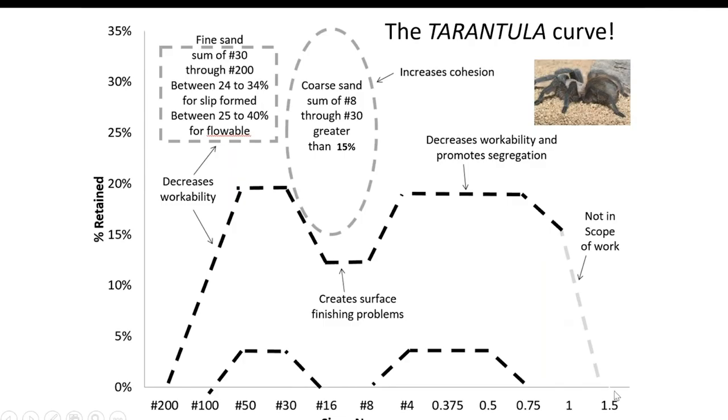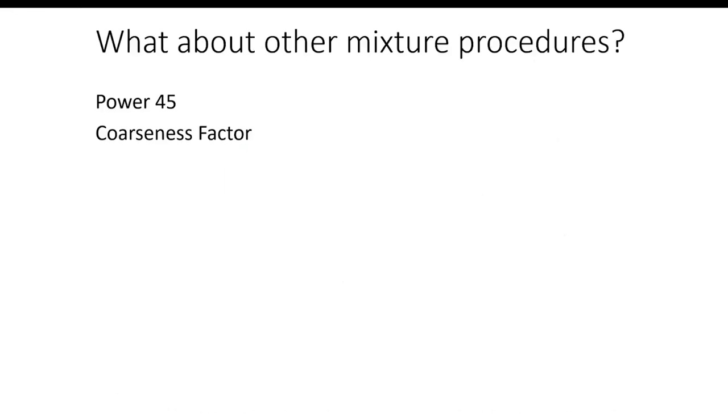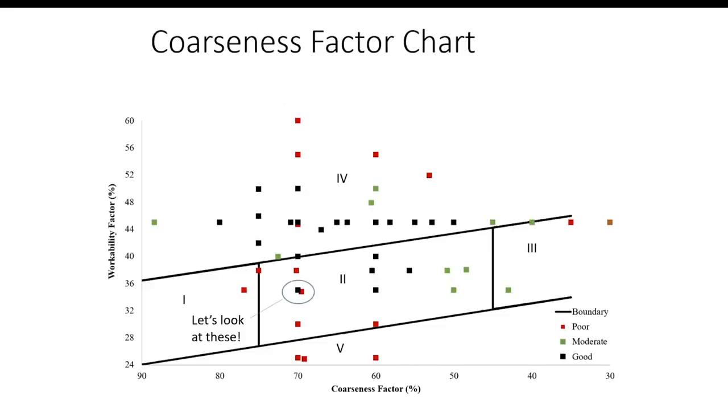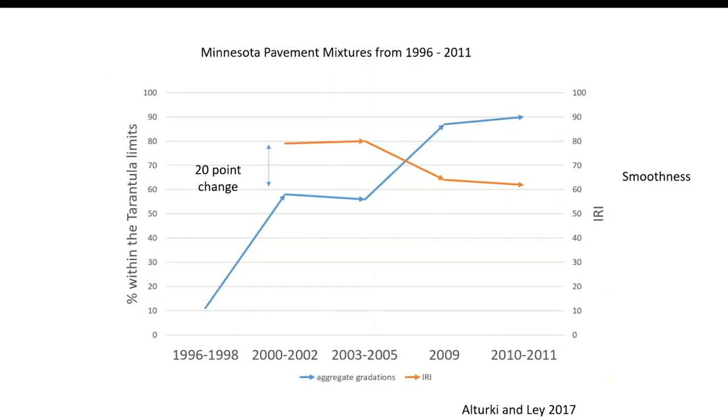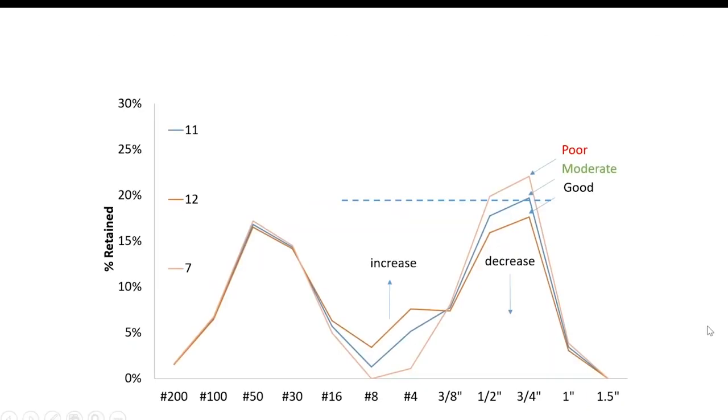But what I can tell you is that I look at that larger stone as another option. You don't need it, but you could use it if you needed to. Let me explain what I'm talking about. The thought process behind the larger aggregate, Tyler, was to reduce paste content or quantity. Right, I understand. So one thing that we're doing for this upcoming project, Gary, is comparing the paste content, the workability, the strength, and the durability with a larger stone and a smaller stone. We're not just doing it with one aggregate. We're doing it with 4 different aggregate sources.